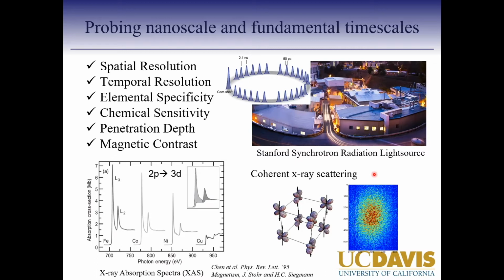For a lab source, if you wanted to get coherent X-rays by putting a pinhole in, you would pretty much be down to zero flux for your experiment. And to get to these nanometer length scales to study these materials and study dynamics in them, this becomes a critical component, and that's something we can get at these synchrotron light sources.